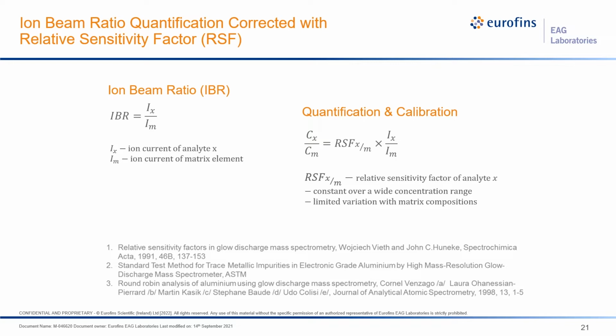Quantification-wise, GDMS uses the ion beam ratio corrected by relative sensitivity factors. For ions, of course, you are collecting ion current, so the ion beam ratio is established using the matrix current as the internal standard. This is not a concentration yet, but using a relative sensitivity factor, which corresponds to the signal generated per ppm atoms, you can generate the concentration of the analytes of interest. This RSF set has two important features. Number one, it is constant over a wide concentration range, and it has limited variation with the matrix composition.